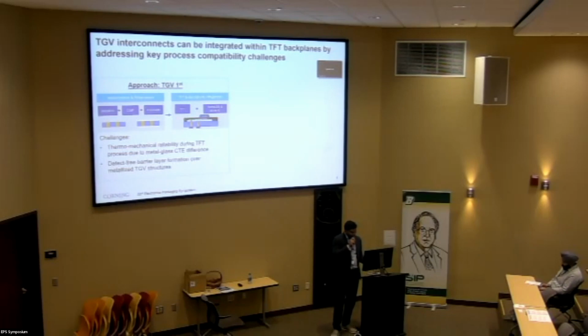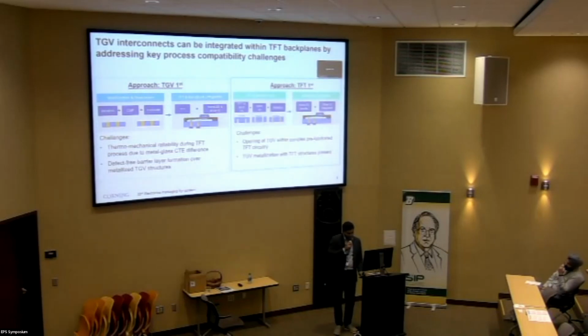But it also comes with the need for a barrier layer coated on top of it. Now you have to control the barrier layer with a different expansion of the sol gel or the polymer in the middle versus the metal on the side wall of the via. So we are still working on it, but it's a very risky approach, and very complex steps need to be solved. The second approach is the TFT first approach.